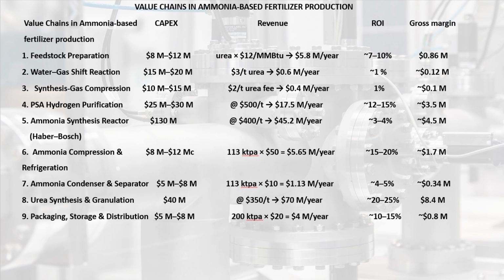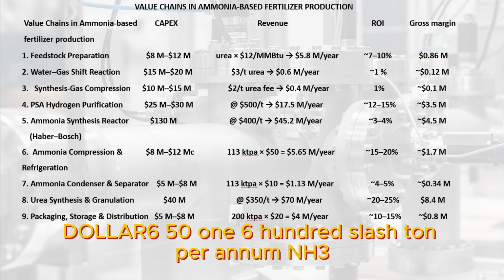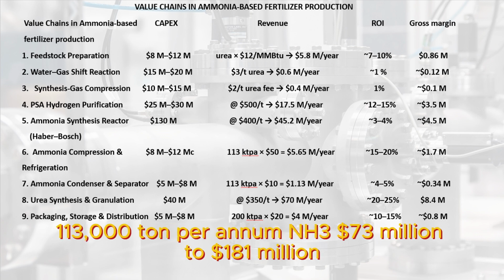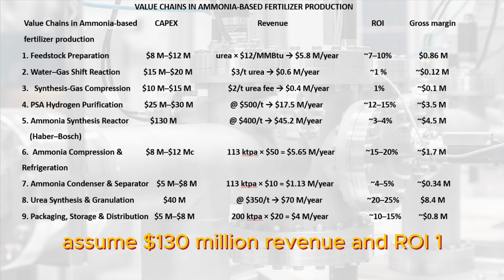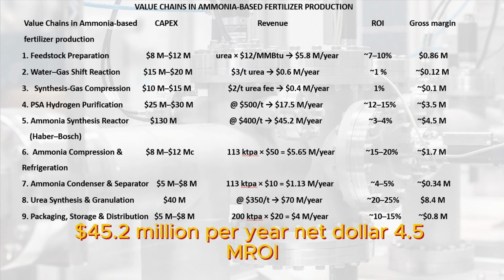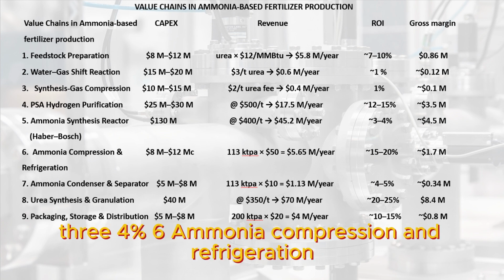The CAPEX $650 to $1,600 per ton per annum NH3, 113,000 ton per annum NH3, $73 million to $181 million. Assume $130 million. Revenue and ROI. 113,000 ton NH3 at $400 per ton, $45.2 million per year. Net $4.5 m ROI 3–4%.